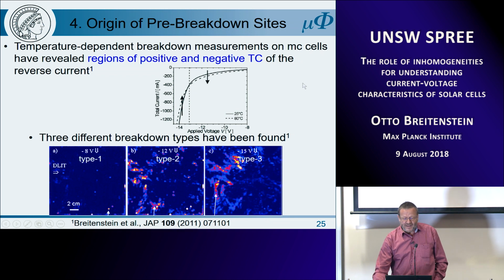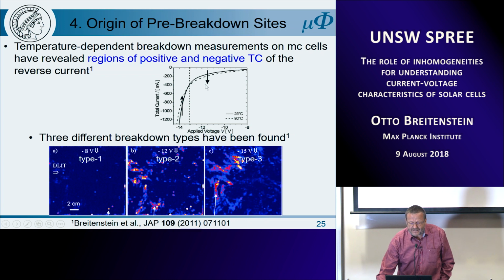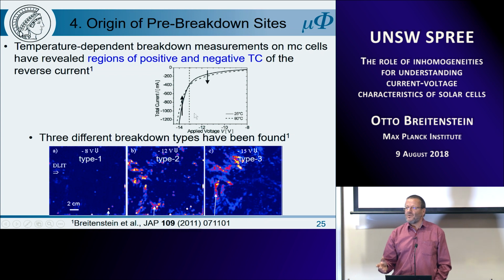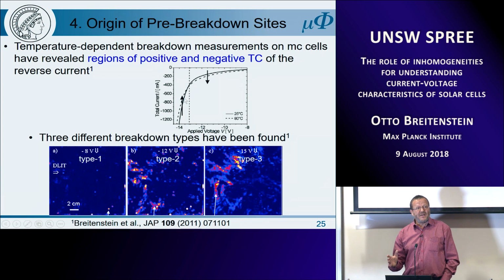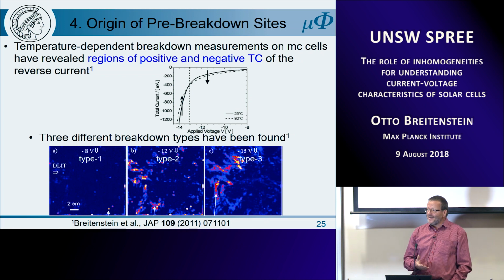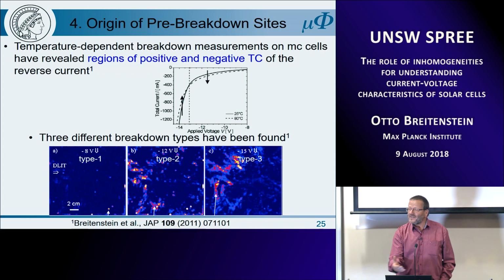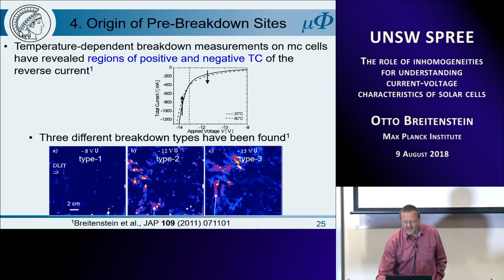And we have found that globally, that's a global dark reverse characteristic, for 25 and 80 degrees centigrade. In the low reverse bias region, we have a positive temperature coefficient of the current, but in the high bias region, we have a negative temperature coefficient. And the only mechanism which leads to a negative temperature coefficient is avalanche. But the voltage is much lower than we expected. And we see also the images are different.